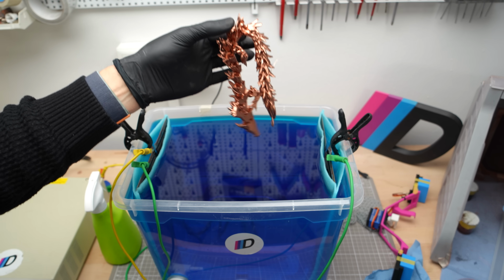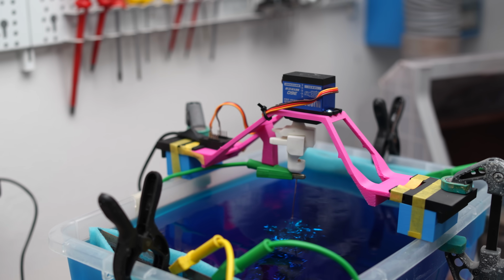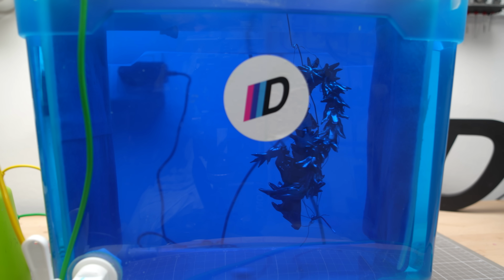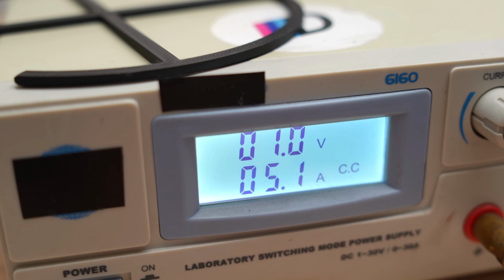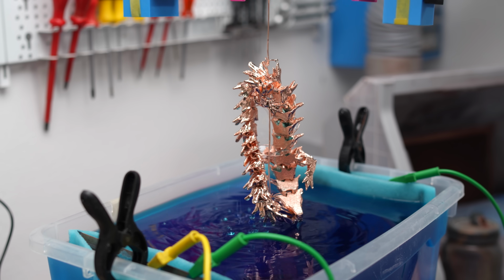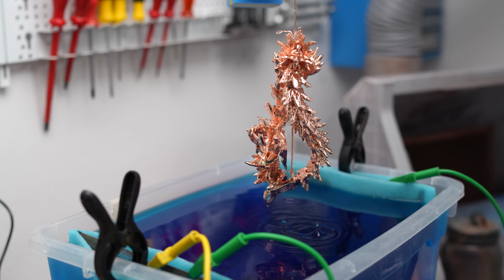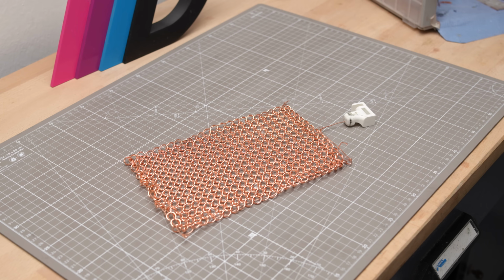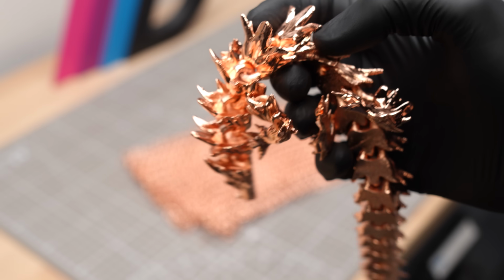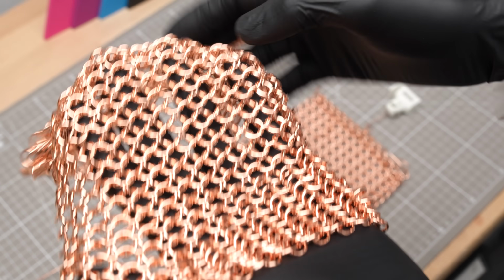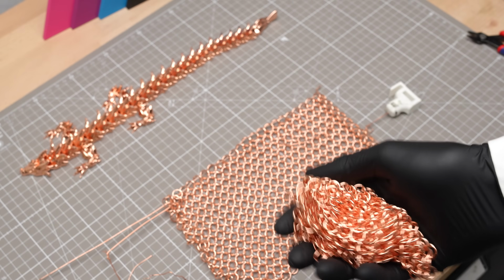I just secured it somehow, let it rotate, and plated it for 4 hours. At 5 amps, it got a really nice copper layer, and the flexible parts didn't fuse together either. That was the hardest part done, and these things already look seriously awesome. They also feel super solid. No surprise, there's quite a bit of mass added during plating.